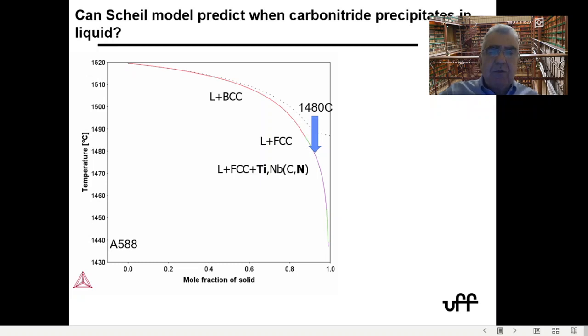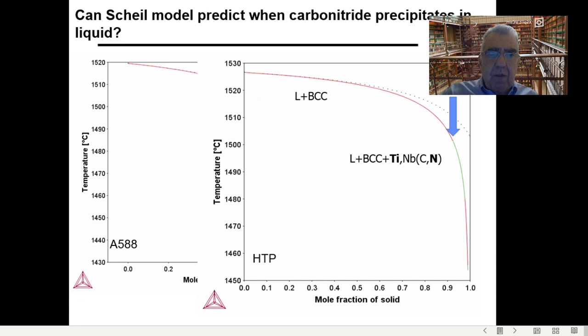So keep in mind, this is going to be large particles. They are essentially niobium carbide or titanium carbonitride that is going to be lost. It's an alloying addition that is not going to be useful for what you're going to do afterwards. And for the other steel, we also get a temperature here where this material with these precipitates form.